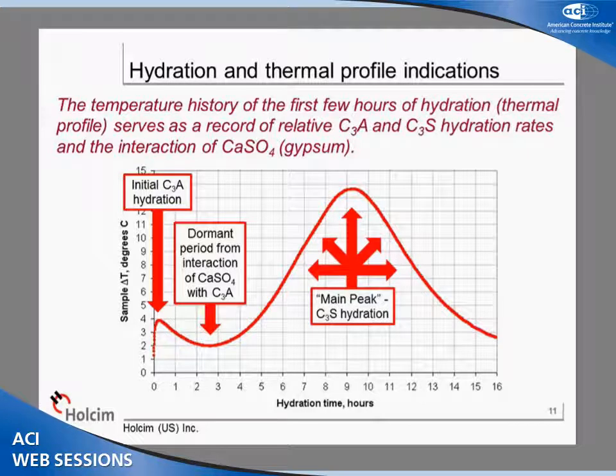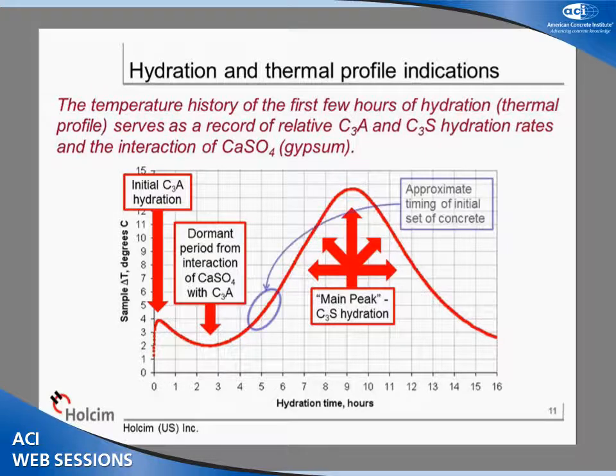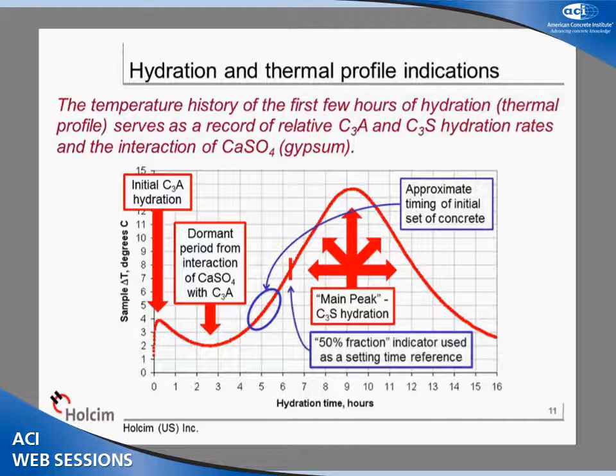And then the main event occurs, which is, of course, the calcium silicate hydration that produces setting of concrete and ultimately the early strength of concrete. We know from experience that in this history of events, the initial setting of concrete probably occurs in this neighborhood of the timing of that sequence. This is actually quite repeatable and has been found to be a useful tool for even estimating concrete setting times from such mixtures. A very convenient reference point would be halfway up the onset of hydration from dormant temperature to peak temperature. It can be done visually or it can be done in a spreadsheet. And we use that just as a reference indicator of approximate setting time changes from one mix to the next.